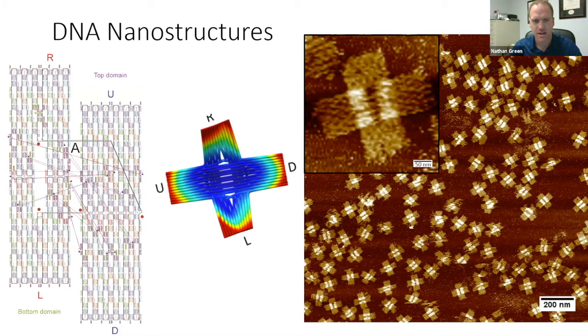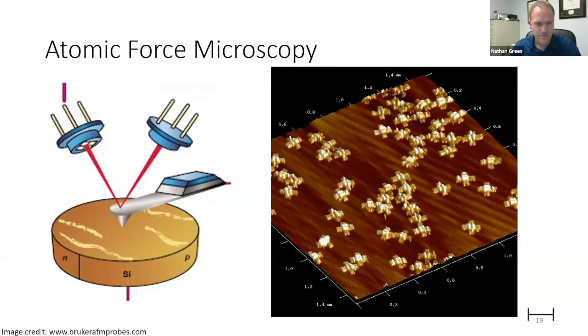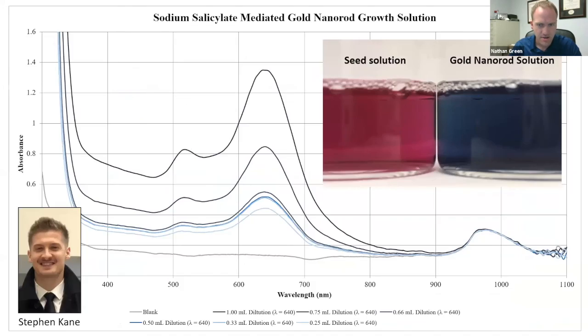the experiment. So I find that from a material side, anytime we successfully make a material, so this image was probably the most exciting thing that I saw for origami. Honestly, for DNA, this blue color was one of the most exciting things that I saw because we knew when we made the blue color that the only way you get gold to be blue like that is to make a gold nanorod that's well defined. And so this took a long time for us just to make the gold nanorods. My students worked on that for the better part of a year.